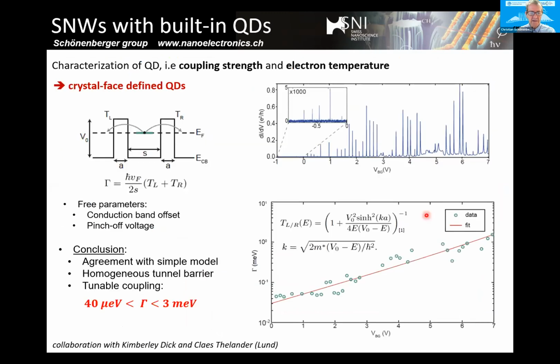So in this particular quantum dot, I stay now with the quantum dots from Lund. What we have is, in our case, just one gate, one back gate. And when you change the back gate, you change the level, the quantum dot level, but you also change the doping in the leads. So if you go to large gating, then the Fermi level goes up above the conduction band, and this would be the Fermi level in the lead. And now you can also move the dot around. You should just remember that we also change the chemical potential in the lead. And if you go to large doping, then what you will reduce is the barrier height. And if the barrier height comes down, then the coupling from the dot state becomes larger.